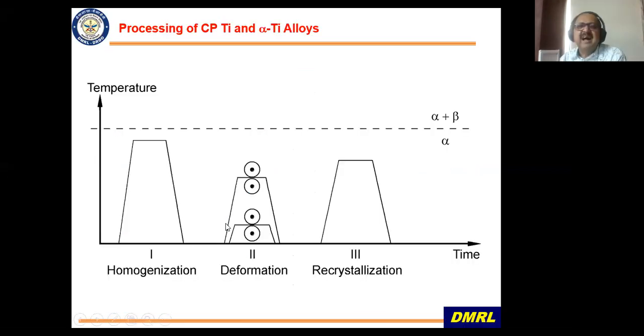Now, how are these alpha alloys processed? First, it is homogenized in the alpha regime itself, that is heated, and then deformation, that is forging, rolling, everything is done in the alpha phase field only, and then recrystallization heat treatment also in the alpha phase field. Temperature you can choose depending on the grain size that you want, so the recrystallization temperature also is in the alpha phase field, and this is how commercial purity titanium and alpha alloys are processed. Very simple processing, not much.